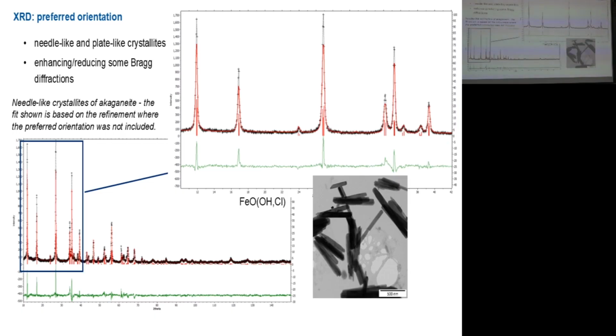So let's go further. Preferred orientation. I would say this is a trivial effect if you have some needles or some platelets in your samples. If the crystals are of this form, then maybe during the sample preparation they will assemble in some preferred orientation, and this will affect your XRD pattern, because you would like to measure XRD pattern with all random orientations. But if there is some preference for assembling the flat crystals in a certain manner, it will be distorted. But you can involve this effect in the analysis, but it can somehow complicate the thing.